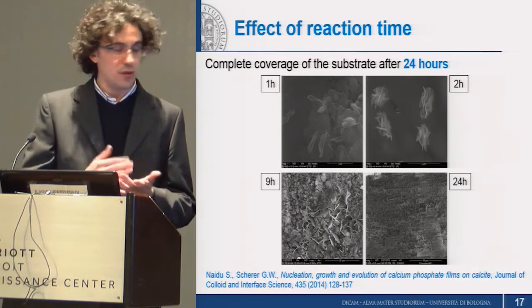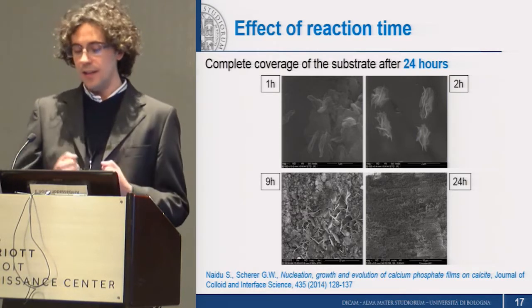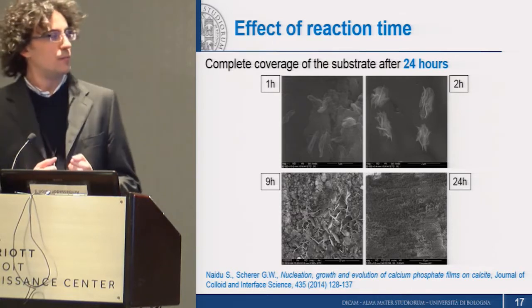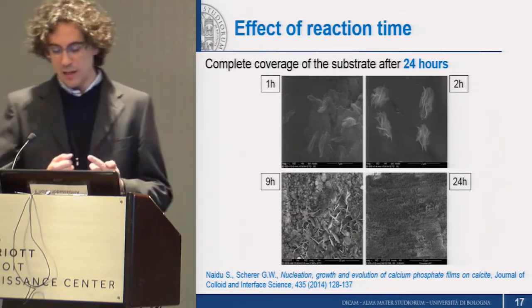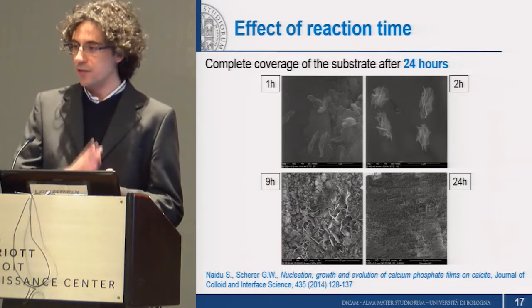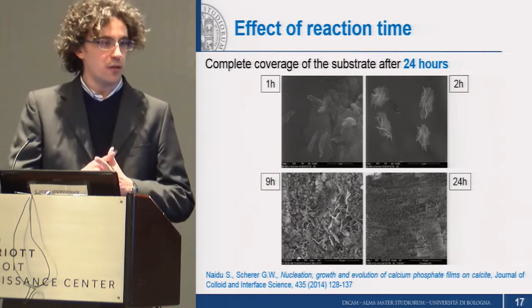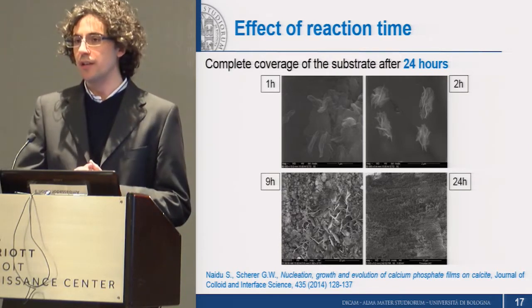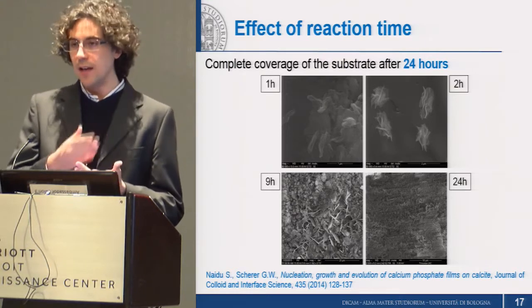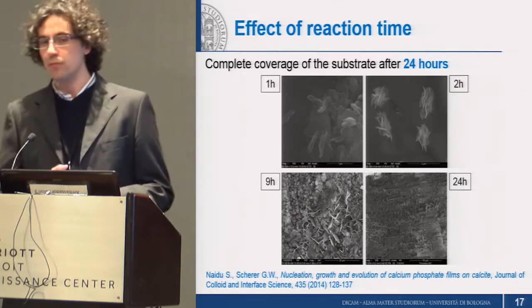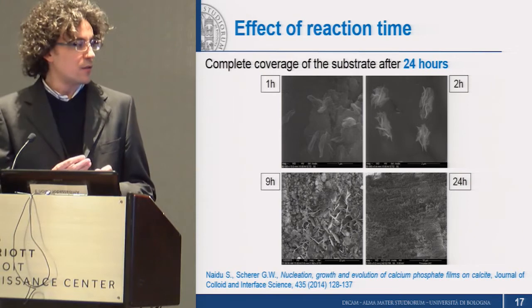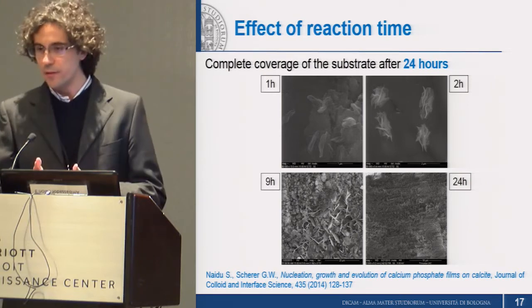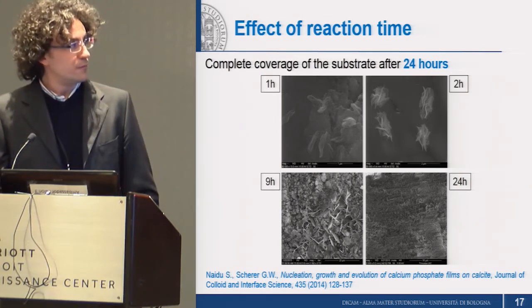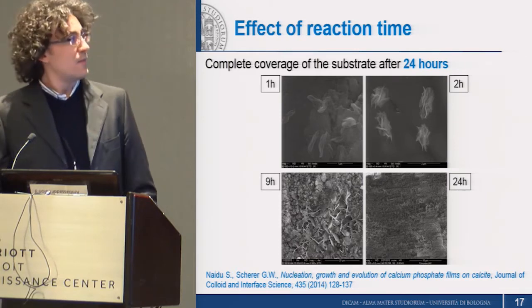coverage of marble, which is positive because for, let's say, the standards of stone treatment, so stone consolidant, 24 hours is a very short time because the most widely used consolidant, which is the ethyl silicate, takes at least 4 weeks to complete its hydrolysis condensation reaction, so 24 hours compared to 4 weeks, it's a very short time.